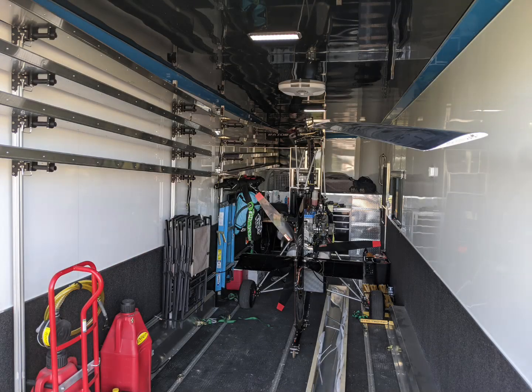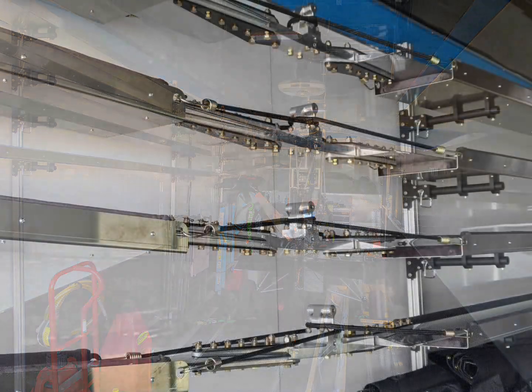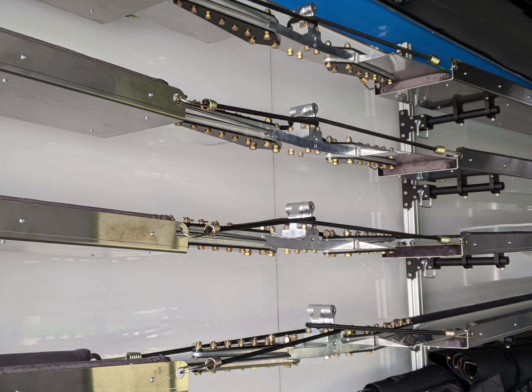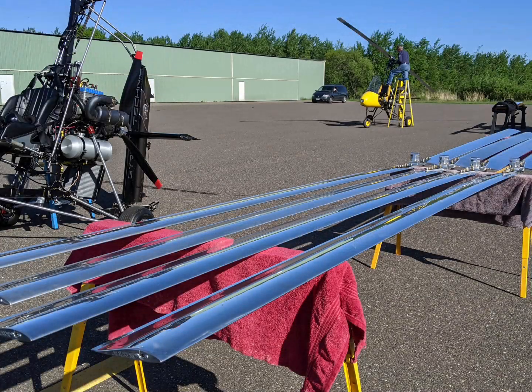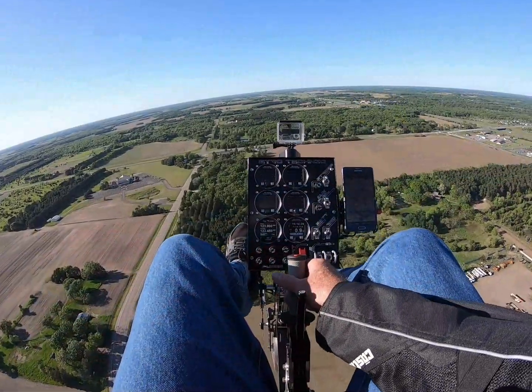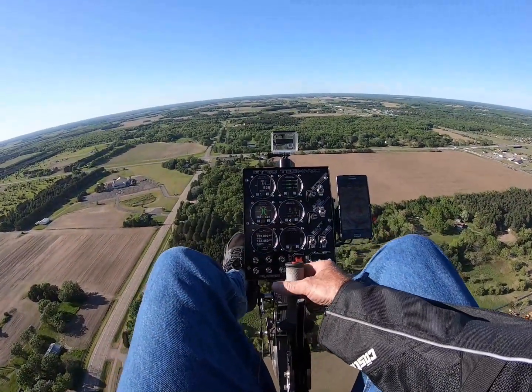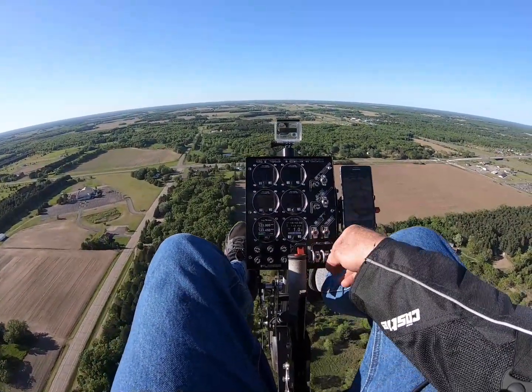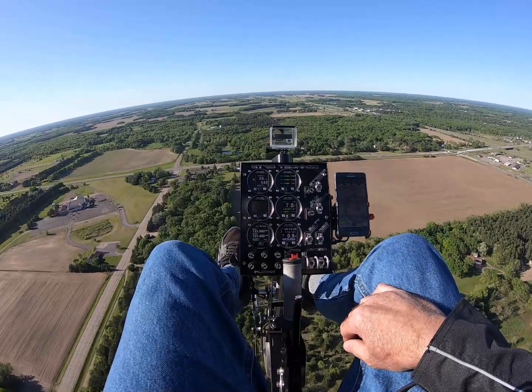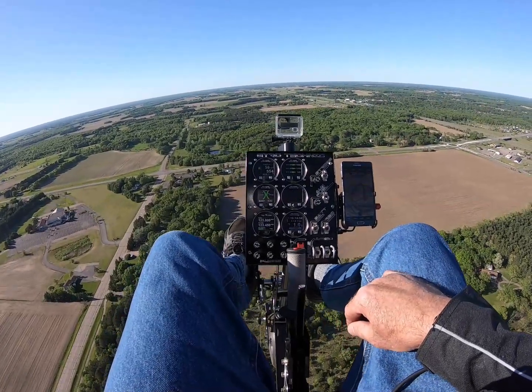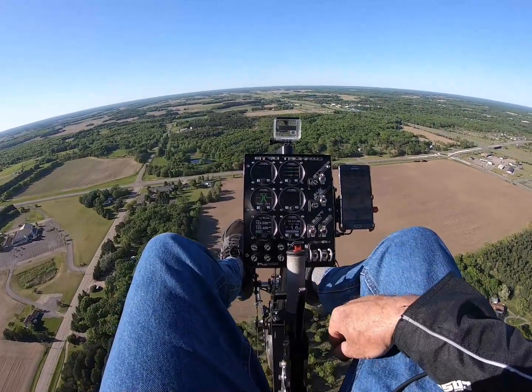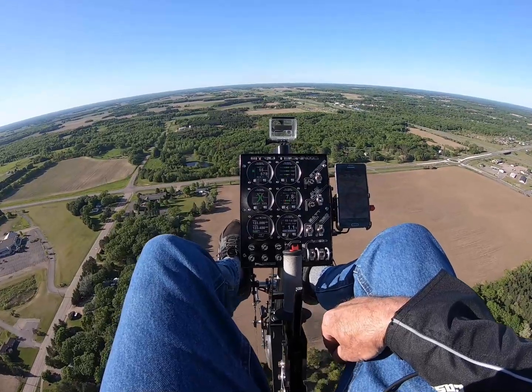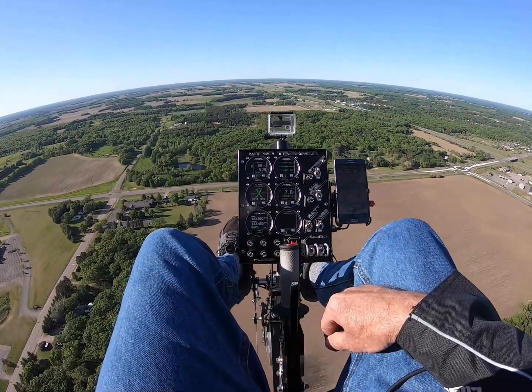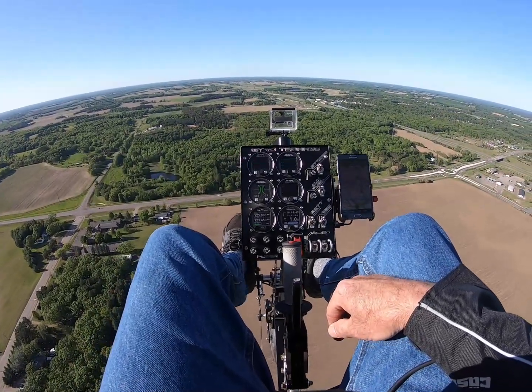Once all the calibration is complete, it's time to load them up and take them to the airfield for testing. We do the testing on our own GT VX series gyros, Dominators, Air Commands, and others. This video shows the result of the first flight tests with a set of 25-foot razor blades. Now you can see the amount of stick shake here. This is with the blades just out of the box per se, with the only calibration I showed earlier performed in this video. No additional dynamic balancing has been done at this point.